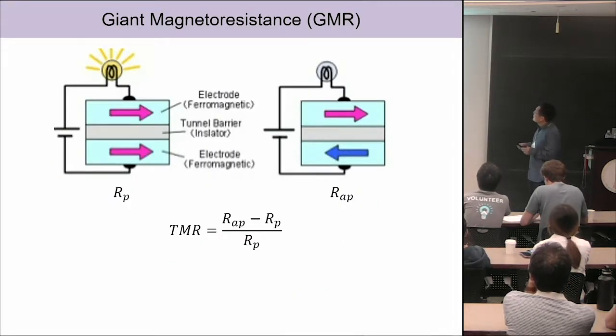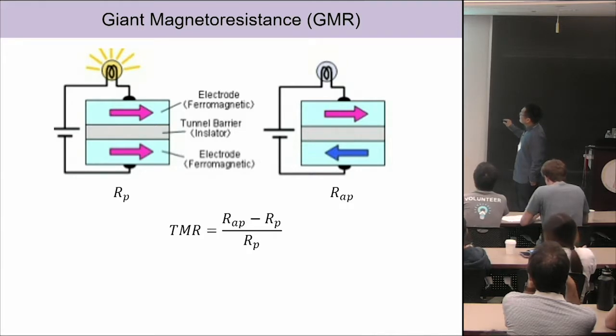Okay, so the example I'm going to tell you is this giant tunneling magnetoresistance with the spin filter effect. What that means is we know this GMR effect, right? In the traditional GMR, you have two ferromagnetic contacts and a tunnel barrier, which is non-magnetic. It depends on the relative orientations of these two ferromagnetic contacts. They can be parallel or anti-parallel, right? From there, we get this ratio of resistance, and we get a tunneling magnetoresistance, TMR.